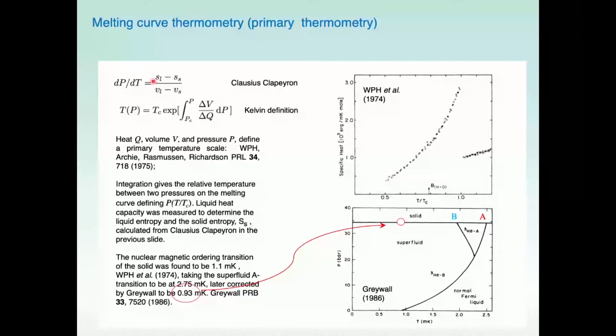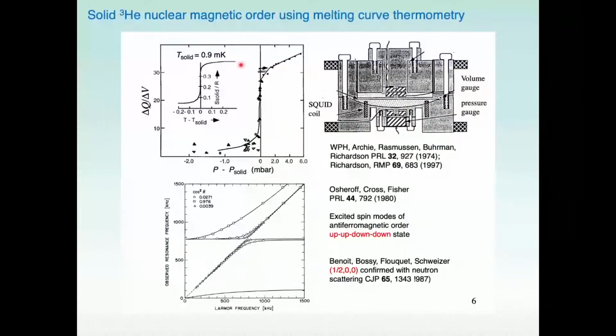The molar volume differences are well known, and therefore you can extract from the measurements, again, in the same temperature scale of the slope of the melting curve, you can extract the solid entropy. And there, a rather interesting thing happens. At somewhat lower temperatures along the melting curve, again, it's flat on this scale, something happens here around 1 millikelvin. What happens is that the entropy shown here in the inset of the top figure drops suddenly.